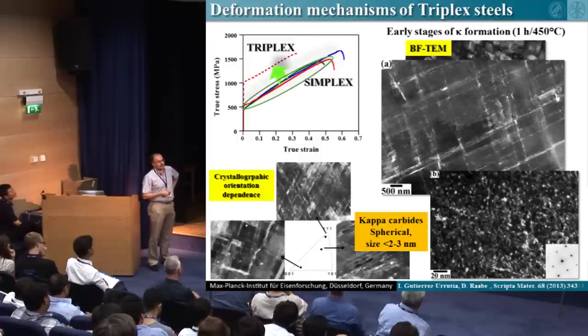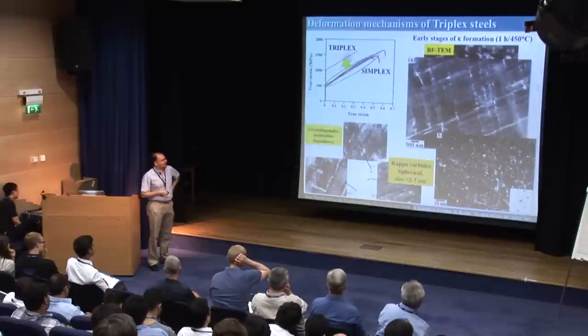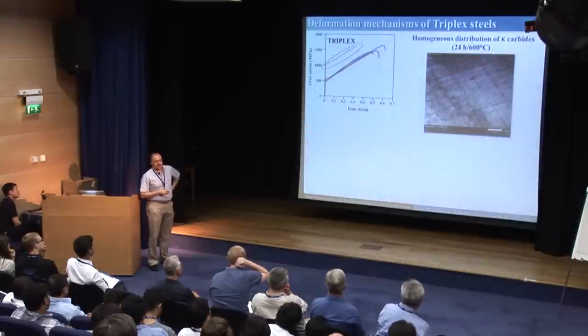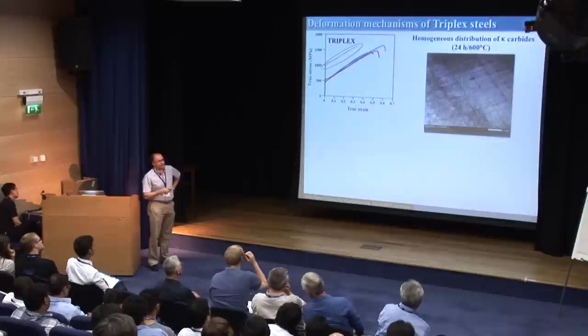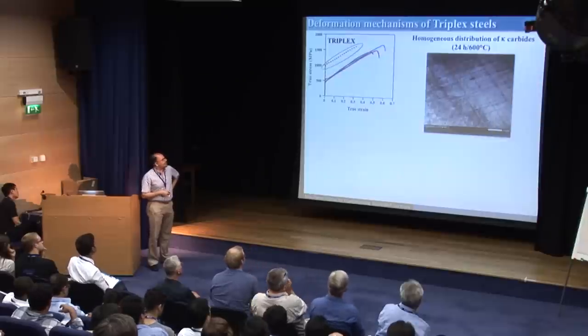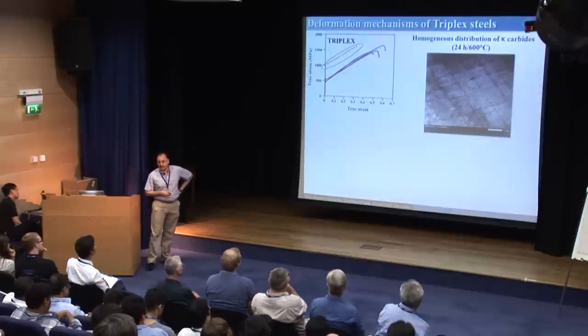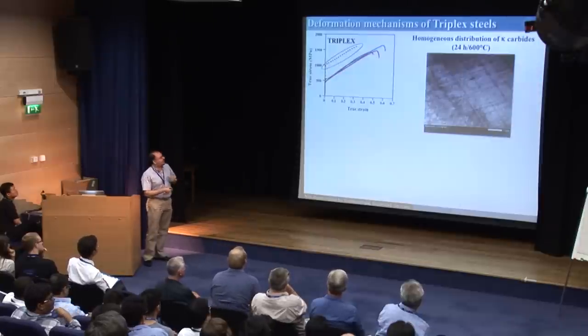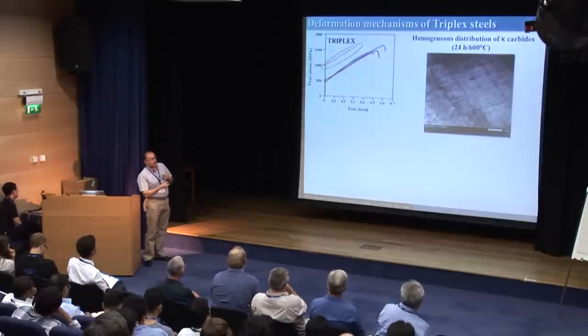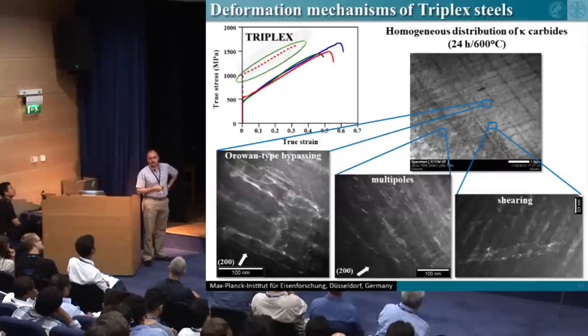So basically here we have a highly alloyed alloy in solid solution. Now if we go to the formation of kappa phases, for instance, 24 hours, 600 degrees, what we are currently doing is analyzing the formation mechanisms. One can immediately see in terms of properties, the yield stress is like a factor of 2. And it's also moderate, quite good ductility. So this is what we are currently evaluating, the deformation mechanisms.